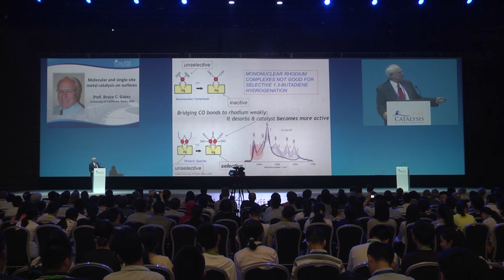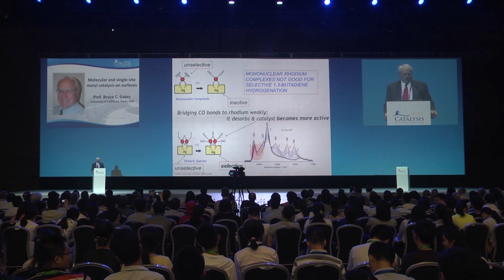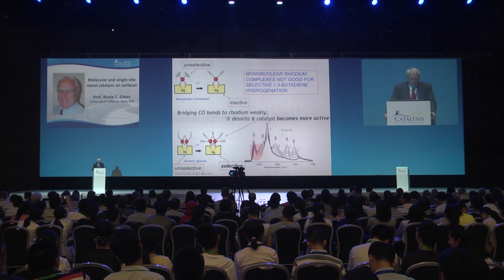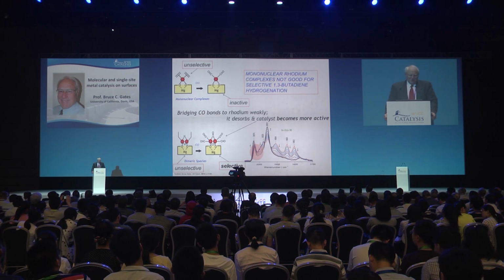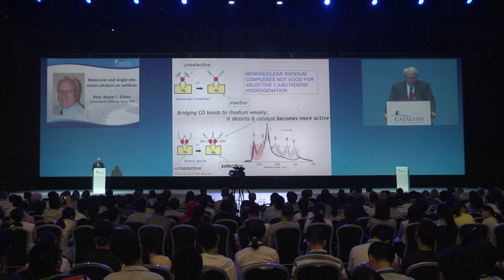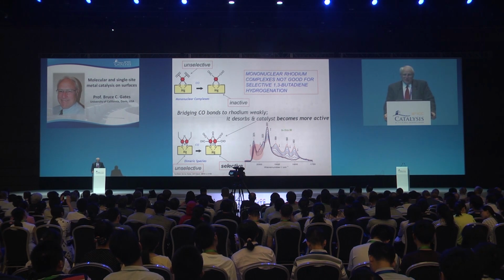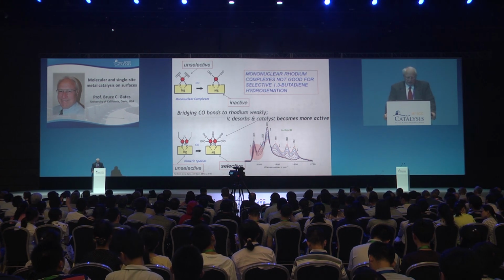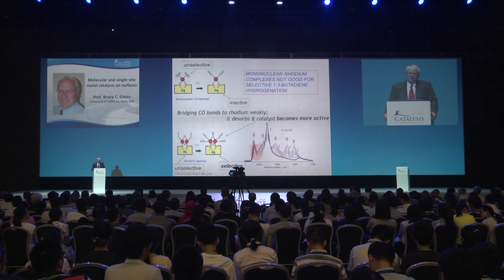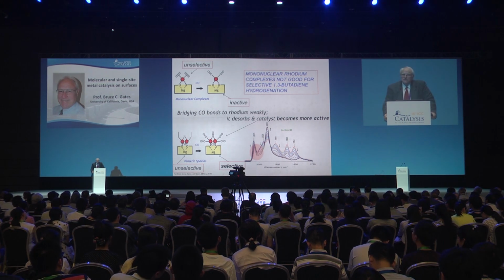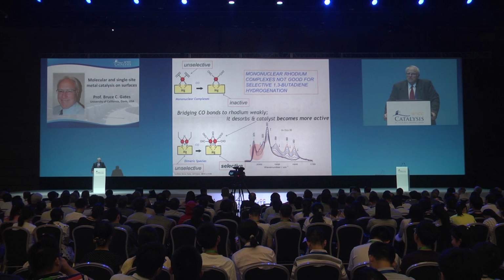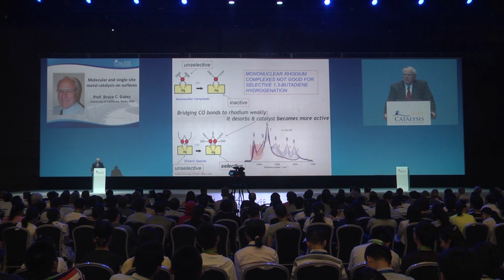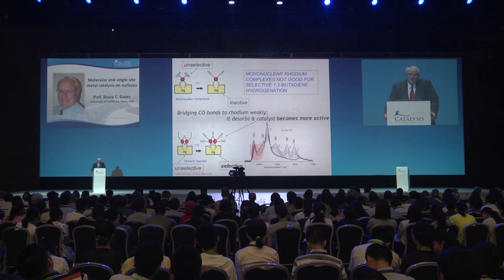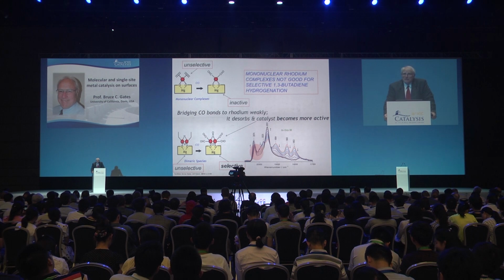That characterization isn't sufficient to determine the structure fully, but it's clear from the EXAFS that it's a dimeric species, catalytically active for the hydrogenation, but unselective. Now we selectively poison that with CO, and we've got a less active, but highly selective catalyst.